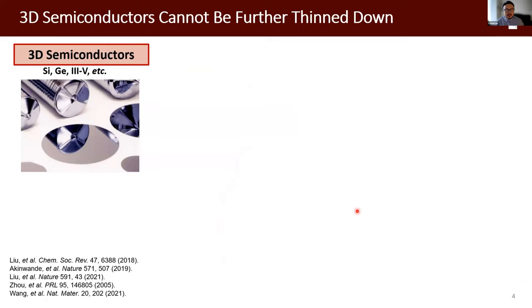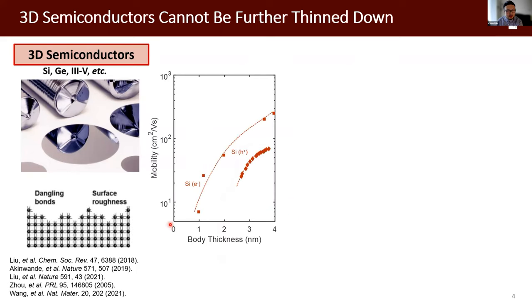For 3D semiconductors like silicon, germanium, and III-V semiconductors, if we shrink down the body thickness further, because they are 3D semiconductors, the surface would be full of dangling bonds and surface roughness. This would cause severe scattering of the carriers in the semiconductor, which leads to huge mobility degradation as we thin down the body thickness to below 5 nanometers.